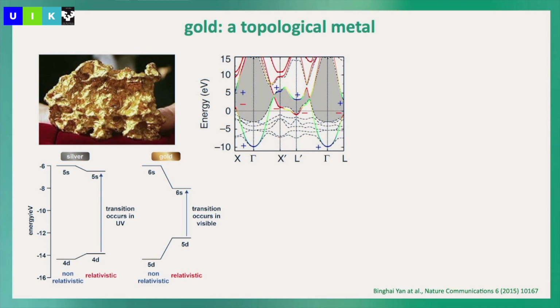And this is one of the, for me, big reasons why all these heavy element compounds have a topological band inversion, because the 6s electrons and the 5s electrons are quite low in energy, so they overlap then with the p electrons from the valence band, the conduction band, and then you get easily this band inversion, which you see here in the band structure of gold. So if the Fermi energy would be here, you would even have nearly a band gap in gold.